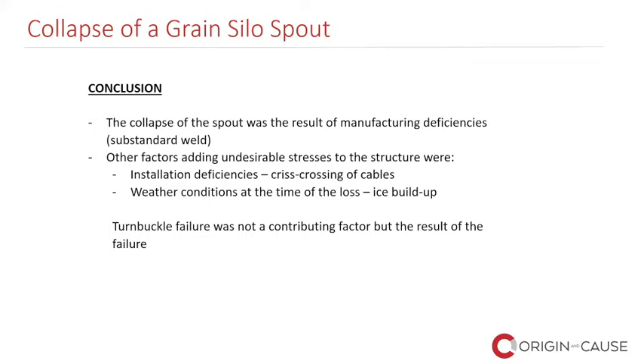And also there were other factors adding undesirable stresses to the structure, which are crisscrossing of cables, which was an installation deficiency, and ice buildup due to weather conditions. However, it must be said that these factors acting alone would not have caused the incident. The main contributing factor to the incident was the substandard weld. And as I mentioned earlier, the turnbuckle failure was not a contributing factor, but the result of the failure. As far as I know, the matter was settled favorable to our client, which was the insurance carrier for the silo owner.